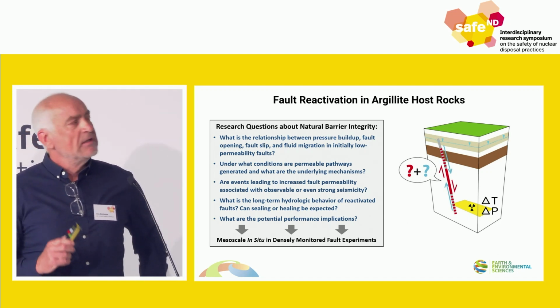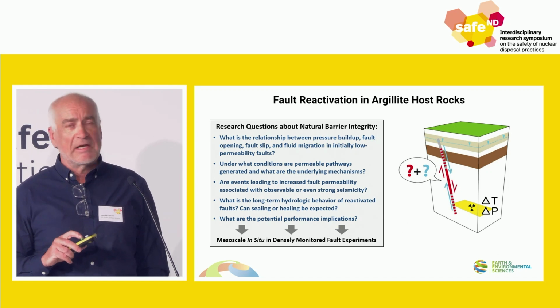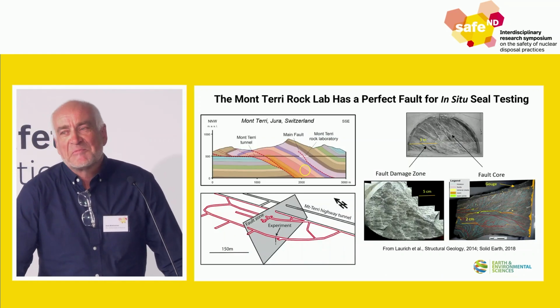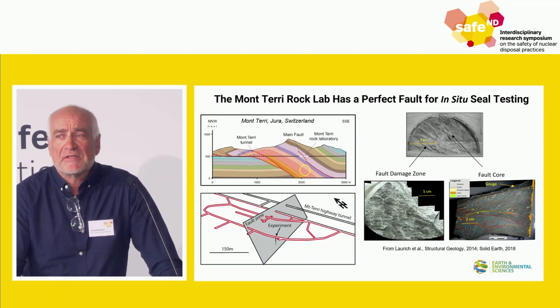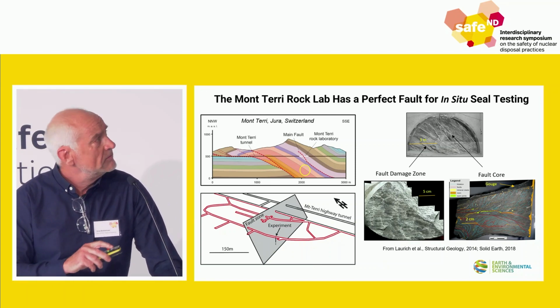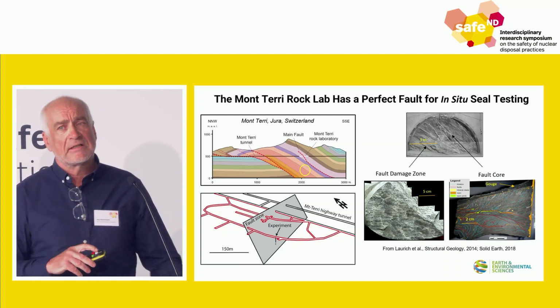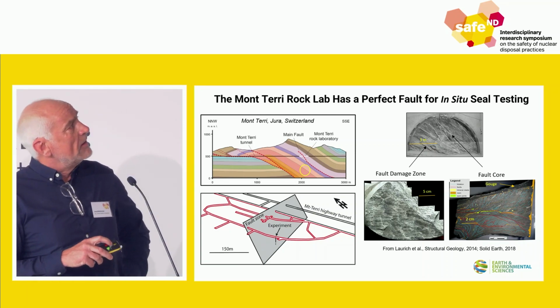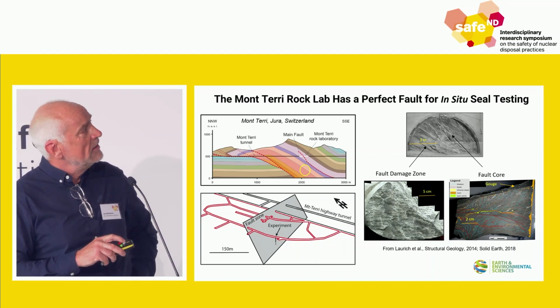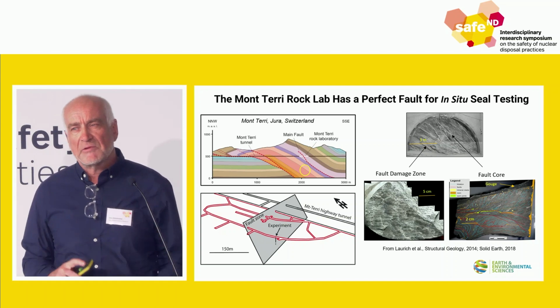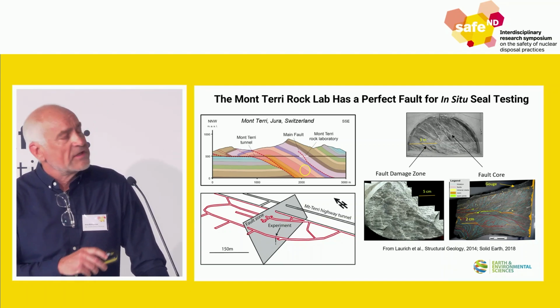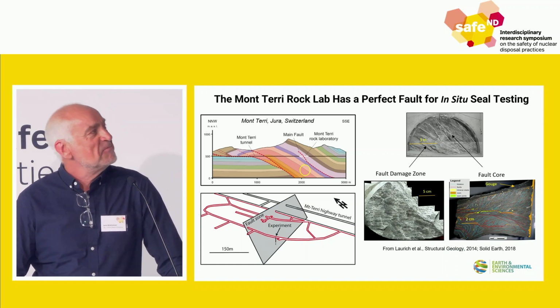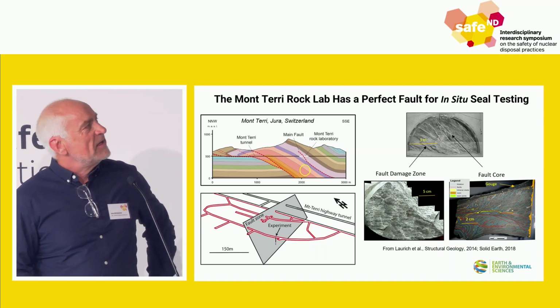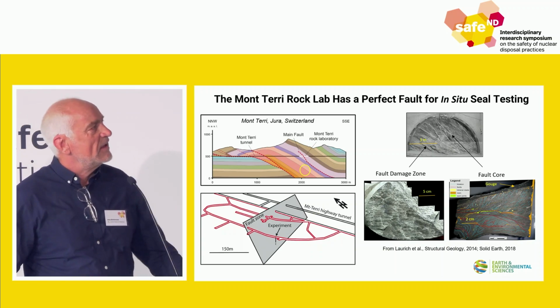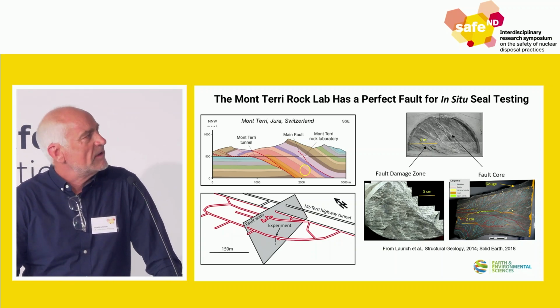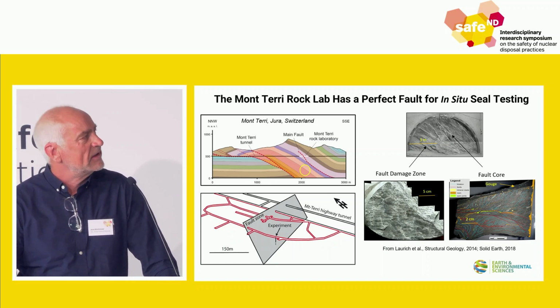We decided to go into an in situ experiment, and we were lucky to find this beautiful fault in the Mont Terri Rock Lab in Switzerland. It's essentially a system of tunnels that cuts through the Opalinus clay. There's a fault that actually cuts through some of those tunnels, so you have direct access to it. You can look at the structures and realize the fault is really not a simple plane - it's usually a bunch of sliding planes potentially. There's a damage zone, there's slickensides, there's some core gouge material that acts geomechanically different.